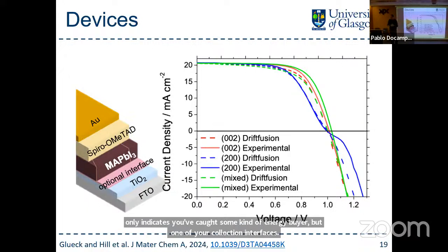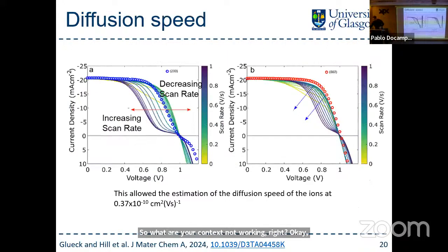So we looked into that. It wasn't that. What we did is that by minimizing the number of defects, picking out the grain boundaries, we slowed down ion migration. We just made it really, really slow. And so we actually caught it in a configuration that led to worse charge extraction. So the message here is it doesn't matter if you clean up your crystals to the infinite degree. You can do single crystal solar cells. You still have ions. You can never get rid of them. So you're going to have to work with them. So we started looking into this and thought, okay, great.